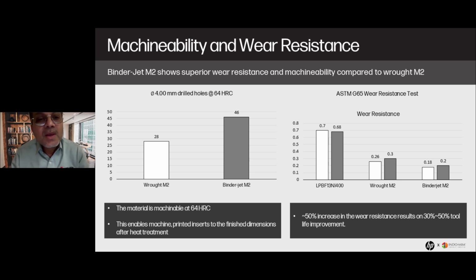But in addition to the tool life study, we also did some fundamental R&D work, trying to compare one-to-one the machinability of the 3D printed M2 material. For the lack of any organized method to understand the difference between the machinability of the wrought and the binder jet material, we just took a big block and started drilling a 4 millimeter hole until the drill bit no longer produced a good quality hole. To our surprise, the wrought material produced only 28 holes at the 64 HRC hardness, whereas with the binder jet material, we were able to take it all the way up to 46 holes without getting into a poor quality of the hole.